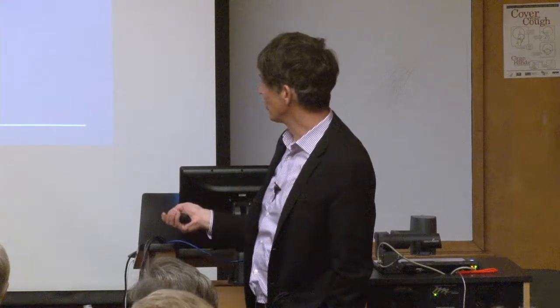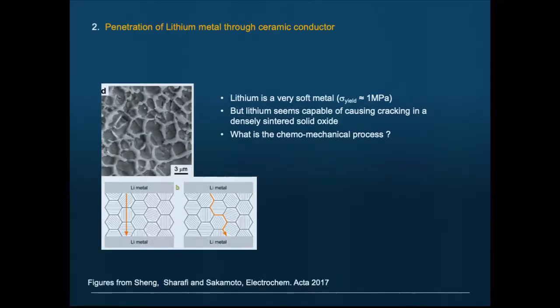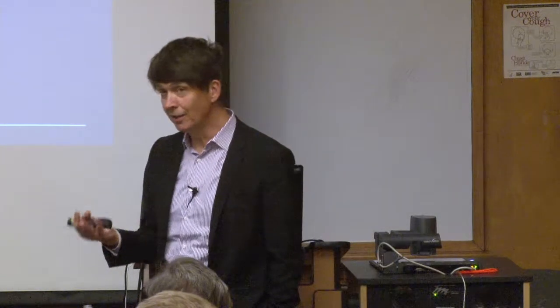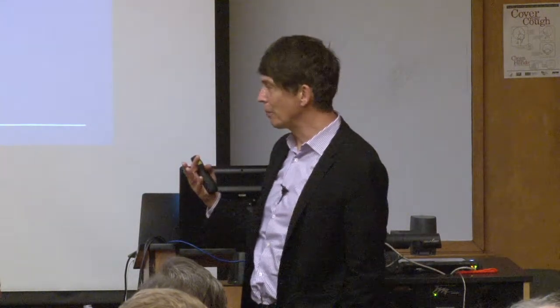Here's a result from Sakamoto's group in Michigan, where this is actually an oxide conductor, but it's polycrystalline. And after a bunch of cycles, lithium has completely grown through the grain boundaries. So this is actually lithium you see everywhere. It's almost like it's etching the grains, right? It's a beautiful picture. So okay, you think it's only grain boundaries, so I'm going to make something without grain boundaries, and maybe you make some kind of amorphous film, or hell, a single crystal. Well, it turns out there's some work now that's shown that lithium fractures a single crystal. And we don't know how that happens. We do not understand the chemomechanics of how a metal that's 0.7 megapascal fractures something with a critical fracture constant that's like hundreds of times bigger, right? And you know, when you don't understand things, people come up with amazingly esoteric theories that maybe lithium gets a lot stronger when it's confined.